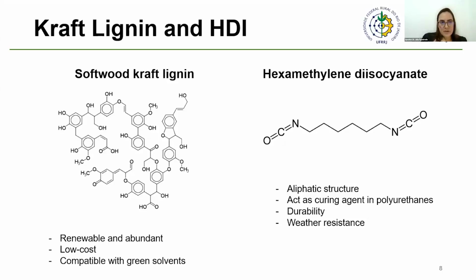The process by which our lignin was recovered was LignoBoost, which is low cost and compatible with green solvents. And we chose hexamethylene diisocyanate, HDI, for its widespread use in coatings, offering durability and resistance, and especially for producing non-toxic amines under degradation.